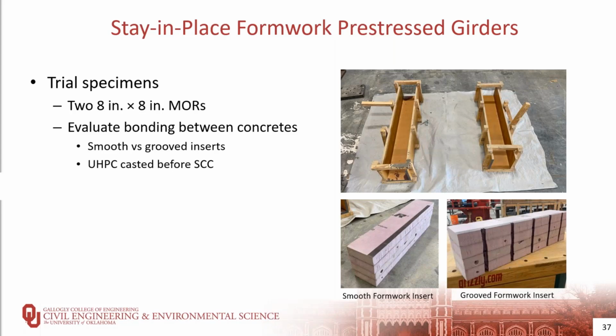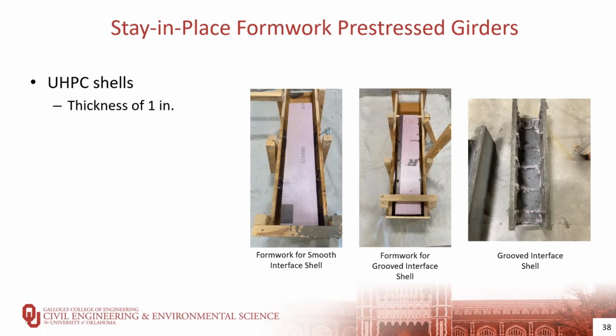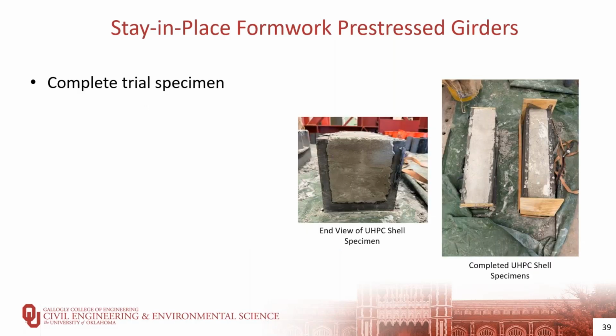Here, foam inserts and MOR formwork were used to create the UHPC shell. And the UHPC shell that was designed is to be 1 inch thick. And here are the pictures showing the foam inserts for both interfaces inside the formwork. The picture on the right shows the shell after UHPC was cast and the formwork was removed. Here are just pictures to show the complete trial specimen, showing the end view of the UHPC shell after the SCC was cast.